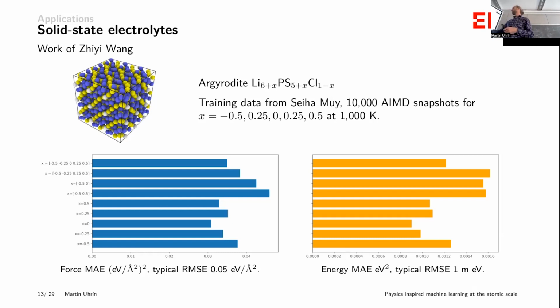So these are in units that are a bit difficult to read because they're square of what would be typical. But let's say for the energies, which is what this is, a typical error that our machine learning model is making is about 1 meV per atom. So the accuracy of the density functional theory, the quantum mechanical approximation we make, isn't much better than this. It's maybe half that at best. So we're already basically down to the accuracy of our original model.